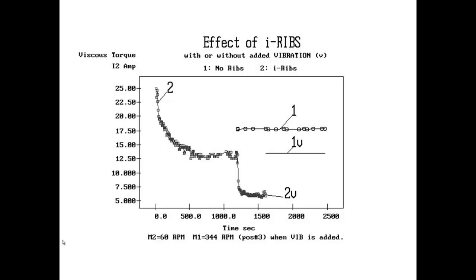So a melt which is extruded but not rotated, not vibrated, with no ribs, has an amperage and a viscosity of 25. And of course you can see the effect of first the rotation, second the external vibration, third the ribs on the surfaces, and the combination of all brings the viscosity to 6, about 4 to 5 times less.